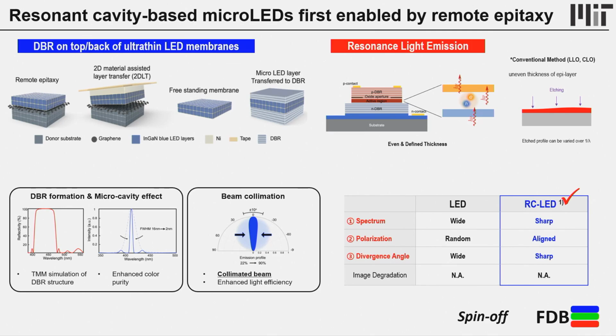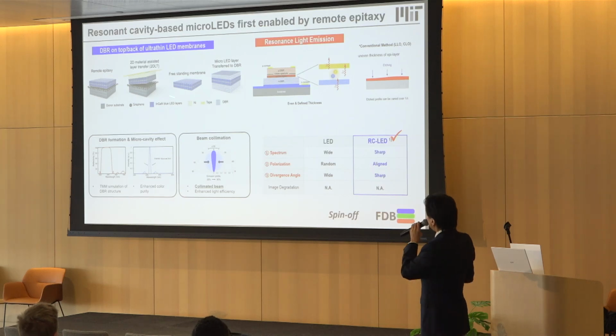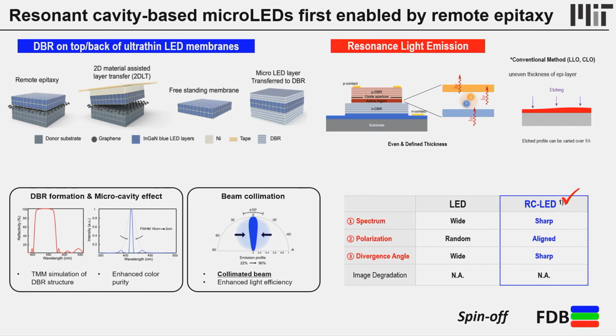we can apply the resonant cavity concept to ultra thin perfect single crystalline LED layers, which could not be imagined before because all the LED layers on the substrate are very thick. We could not imagine applying the resonant cavity concept, but with these ultra thin micro LEDs, you can do that. Simply, you peel off the LED layers out of the substrate, then we can do the DBR top and bottom, a sandwich DBR, after peeling them off. Then what you can imagine is a narrow beam, the wavelength is narrow, and all the beam can be collimated. Okay, so this can happen. Then resonant light emission is possible by utilizing remote epitaxy LEDs.